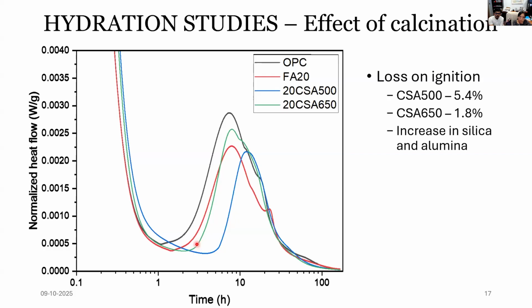Coming to the next, this could be because of two reasons. One is the cornstover ash, which is calcined at 500 degrees centigrade, had a higher amount of unburned carbon in the system, which is almost 5.4%. And in case of when we calcine it to 650 degrees centigrade, the unburned carbon reduced to 1.8%, which correspondingly increases the reactive silica and the alumina in the system.